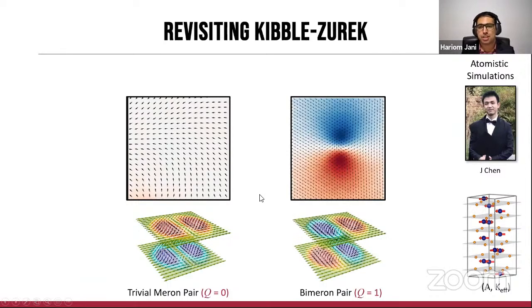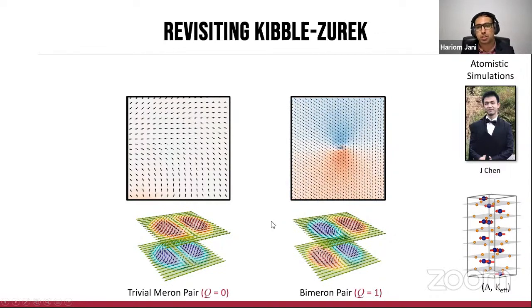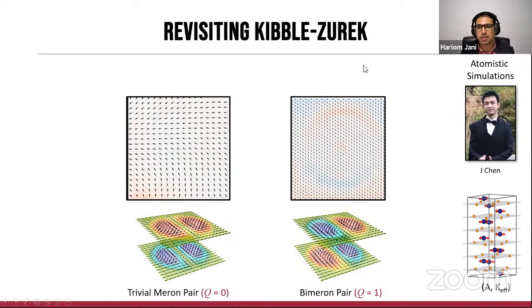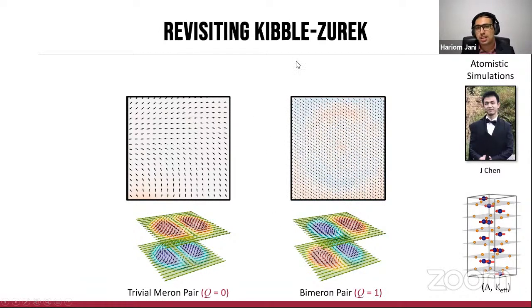Now, something very fascinating happens if we start off with a topologically non-trivial pair. As enforced by topology protection, this object should be stable, but of course, something else actually occurs in the system here. As the cores come closer and closer, there is a whole wave emitted at the end of that annihilation process. I'd just like to repeat that again. You can see the cores come close together and it emanates these waves at the end of this process. This was actually already observed in the case of ferromagnetic texture annihilation between vortices and anti-vortices, but this is a very interesting antiferromagnetic analog of that, which now emits antiferromagnetic spin waves which are present in the system here.